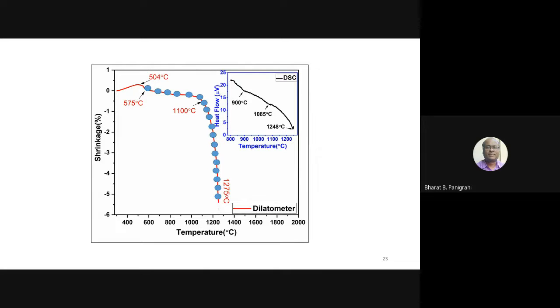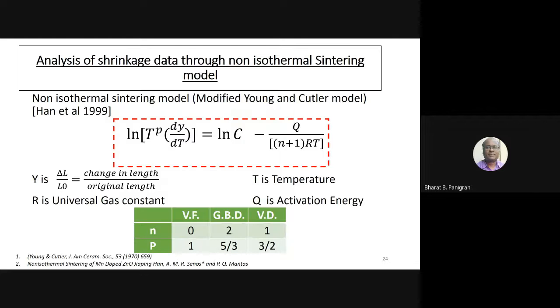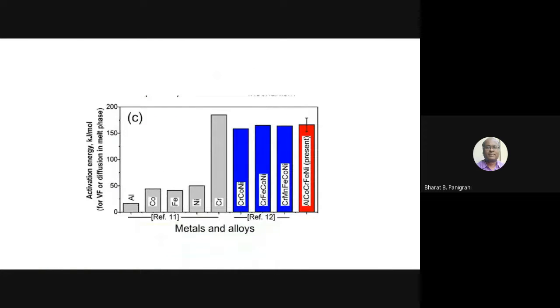To go further, something which is not of much interest to you is called kinetics of shrinkage. There is a lot of modeling we do. When we talk about sintering kinetics, we try to identify which particular diffusion or sintering mechanism is acting for densification. There are a variety of sintering mechanisms, you all know. In this case, I have shown that this particular alloy has a liquid phase forming. Liquid phase forming means the viscosity of the liquid which has formed plays a huge role. To understand that, we have characterized the viscosity of various elements.